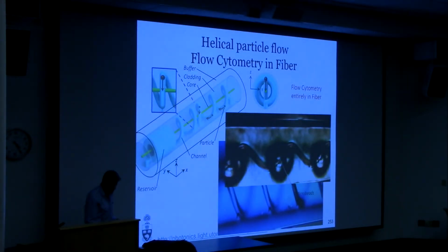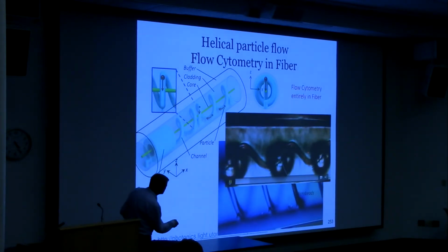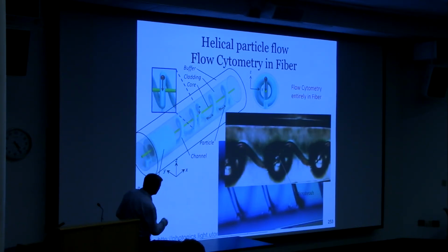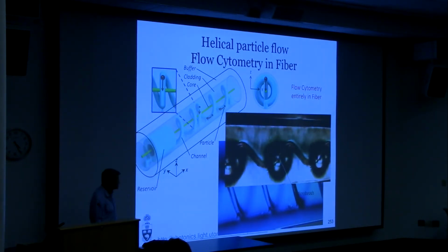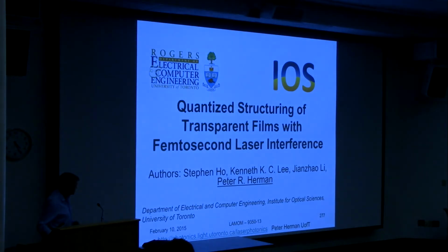I'll just show this result. This is actually writing through the buffer, and we've taken the spiral path and chemically etched it, and then part of the channel goes through the core waveguide. We put in fluorescent beads. It turns out you can sense the beads, and this is just a quick video for the possibility of cytometry in a fiber. You're going to see a bead moving in here. And there it is in the center. This doesn't show the fluorescence, I don't have the video here, but it really lights up, and you can detect the fluorescence along the fiber core. So you can excite and detect along that, and we're just trying to put a paper together on that kind of result. So a lot of really cool stuff.